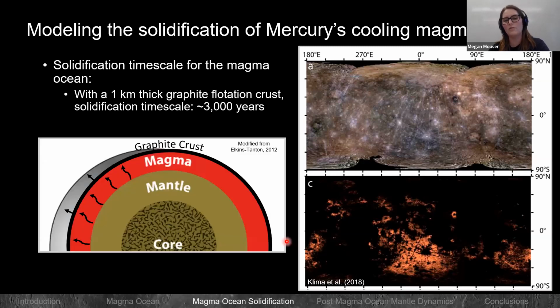So when you have a flotation crust, this scenario is very analogous to what we believe happened on the moon with the anorthite flotation crust, but you now introduce this conductive barrier. So it takes a lot longer for the heat to conduct through that lid and be released into the system. And so in this instance, you're going to have a more elongated solidification timescale. So our estimates are about 3,000 years for this particular scenario. And we're also looking at a 1 kilometer thick graphite flotation crust.